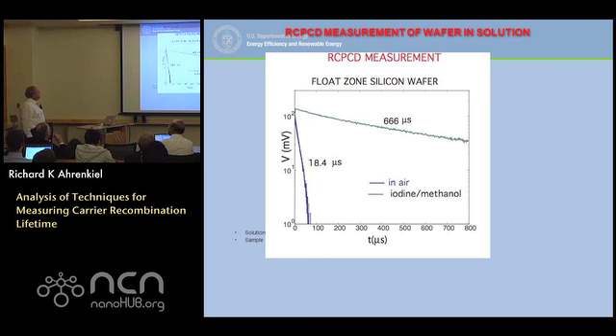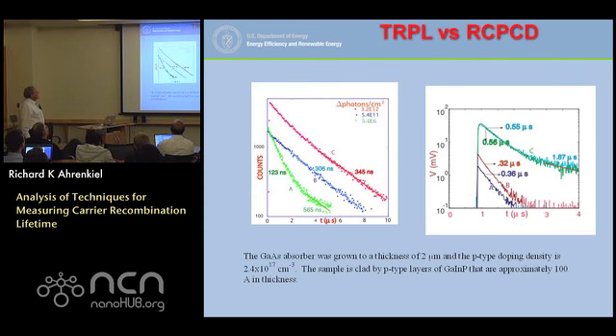Surface has been passivated. And so this enables us, basically we put the wafer in a little plastic vial with iodine methanol, just drop the wafer in, set the whole thing on top, and you go from here to here. So it's pretty spectacular. Other materials have other passivation means, but we won't go into that. Okay, now we get into, do any of these measurements agree?